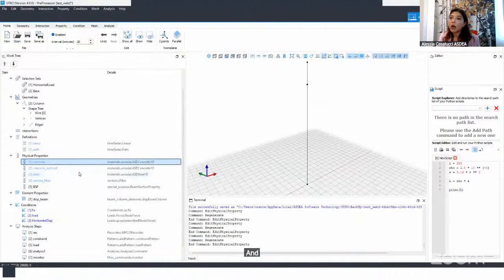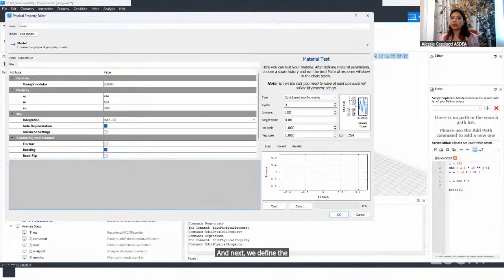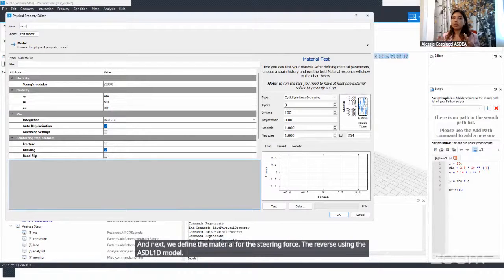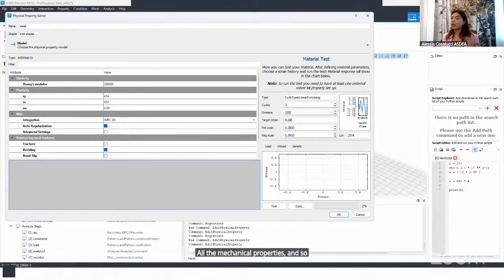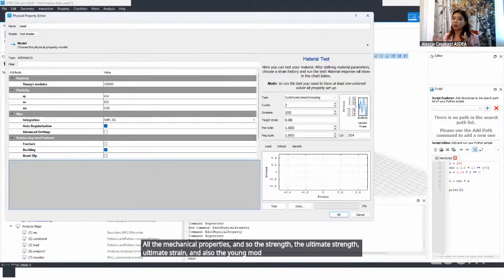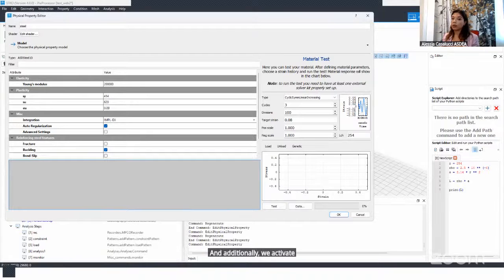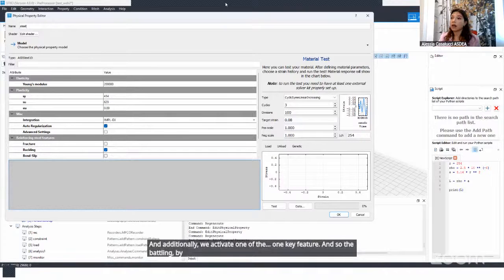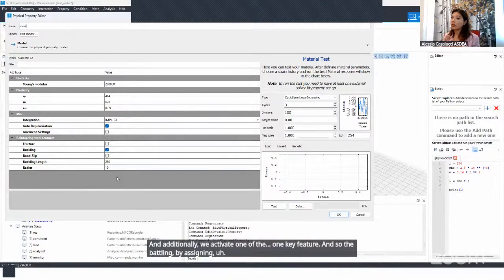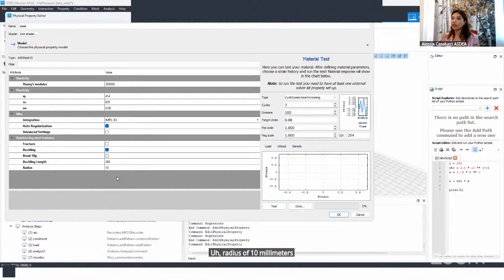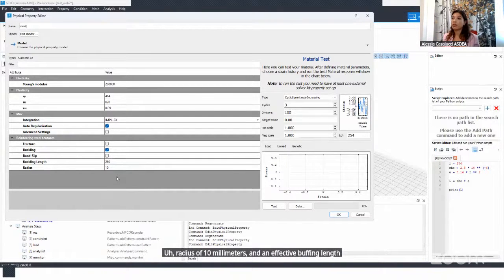And next, we define the material for the steel rebars using the ASDSteel1D model. All the mechanical properties, the yield strength, ultimate strain, and also the Young modulus, are taken from the experimental report. Additionally, we activate one key feature, the buckling, by assigning a radius of 10 millimeters and an effective buckling length derived from the test data.